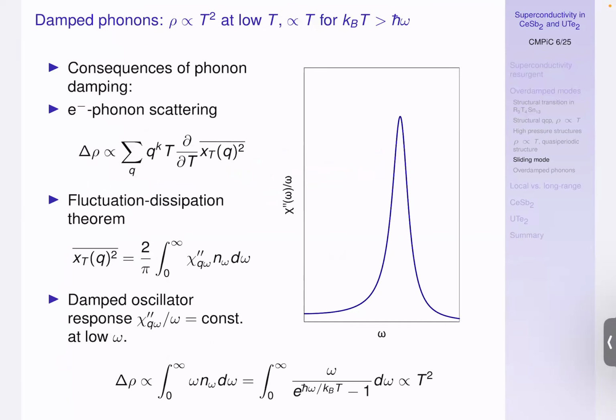So just to emphasize again the point I was trying to make, if you look at electron-phonon scattering in this way, that basically comes out of calculating the variance of the displacement of the atoms. There's a trick, you have to take the temperature derivative, multiply by temperature again, but that basically doesn't change much. And then the variance of the displacement you can get from the response function via the fluctuation dissipation theorem. Now if you look at the response function of a damped harmonic oscillator, and I plotted it as imaginary part over frequency, you notice it has this tail. That's the important thing. It extends to zero frequency. Chi double prime over omega is constant at low frequency.